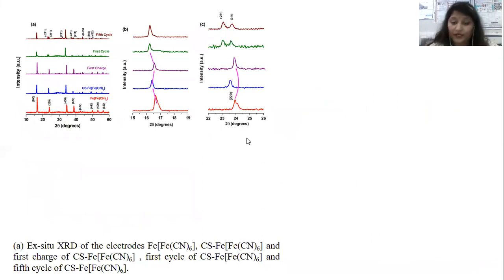So an approach to thoroughly understand in depth the electrochemical properties of sodiated Prussian blue analogues has been implemented through ex situ analysis. The first charge and first cycle in the figure depict the sodiated Prussian blue analogue's first charge XRD and first cycle. First cycle means one charge and discharge. The ex situ XRD analysis gives more insight into the structural changes caused by the electrochemical activity.